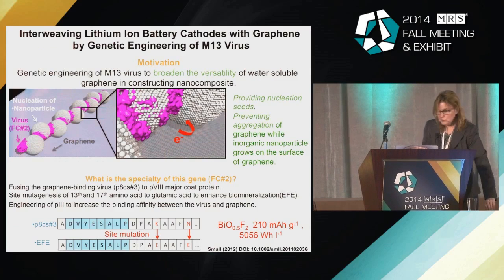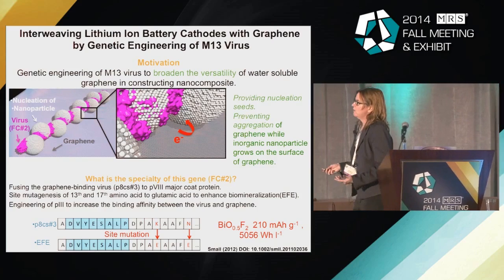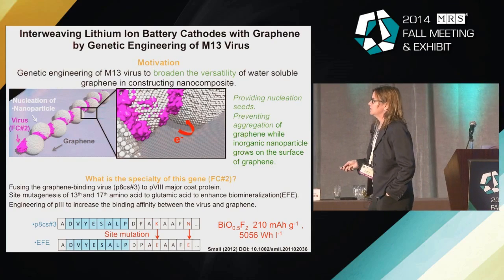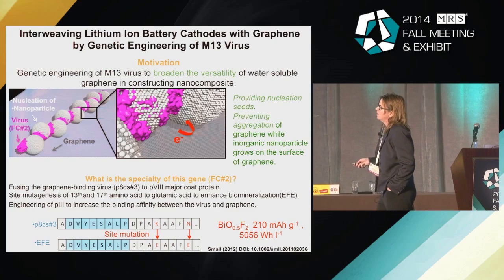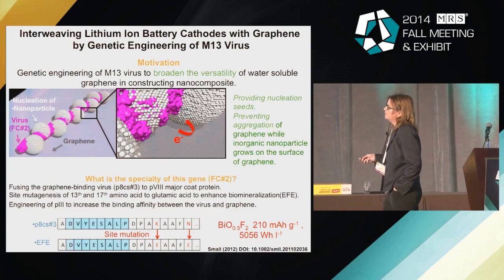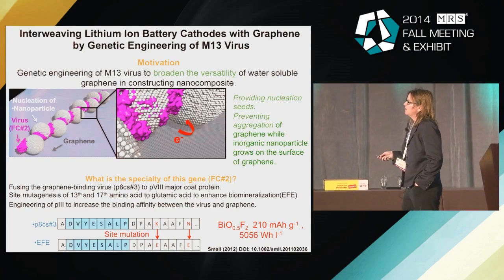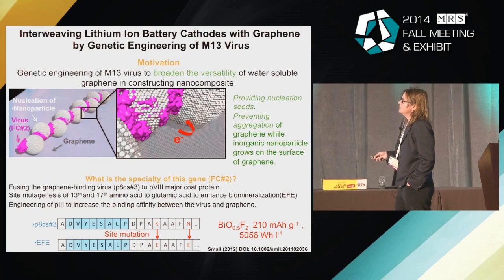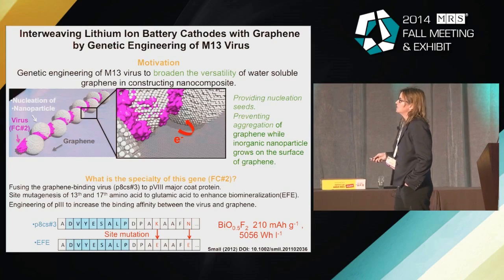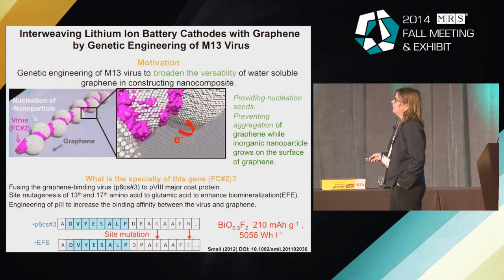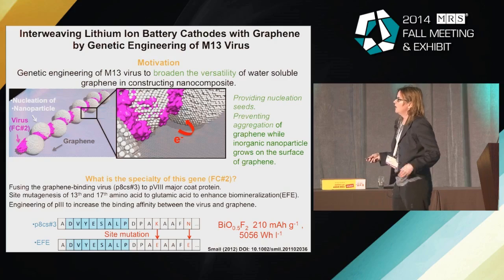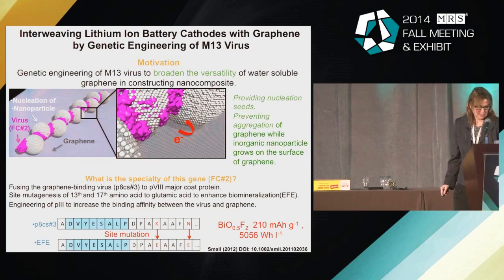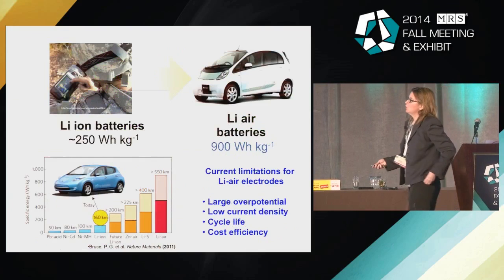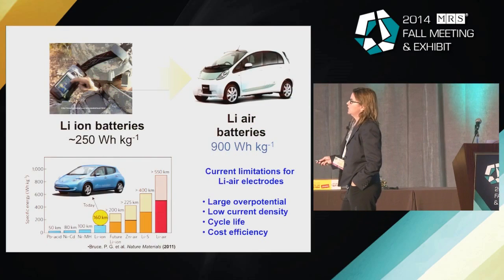Now, we showed that you can bind carbon nanotubes. How about graphene? So that's trying to incorporate the second BioX talk into mine, which is we thought about taking viruses that could bind graphene and give them a second sequence that would simultaneously allow them to nucleate a material. And so this was bismuth oxyfluoride material. And so what we found is that we could find viruses that could bind to this material really well and then nucleate the material of interest. We showed a great enhancement in performance with those kinds of materials.